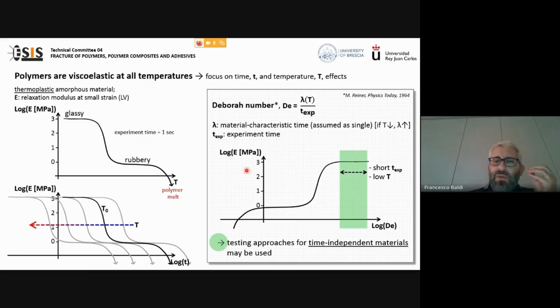Now, if I plot the relaxation modulus as a function of the Deborah number, I can observe that there is a region that is highlighted, that is indicated here as a green area, that is the region corresponding to short experiment time and low temperature, in which region, if I'm able to keep the material in that region, I'm quite far from this transition. Now, this region corresponds to the high values of Deborah number, and this region is the region where the material exhibits a prevalently elastic behavior. Now, if I can stay in this region, in the green region, I can apply the testing approaches for time-independent materials also to our polymeric materials. Therefore, the material is viscoelastic, of course, but at least I can try to apply the testing approaches specifically developed for time-independent materials.